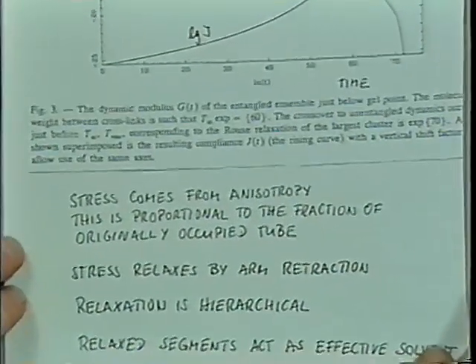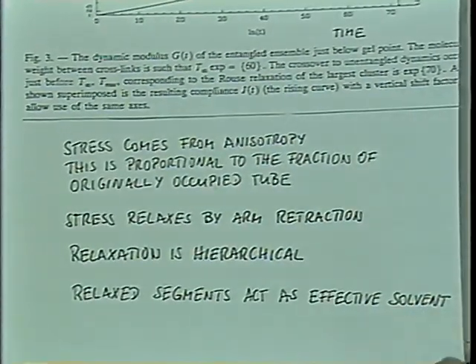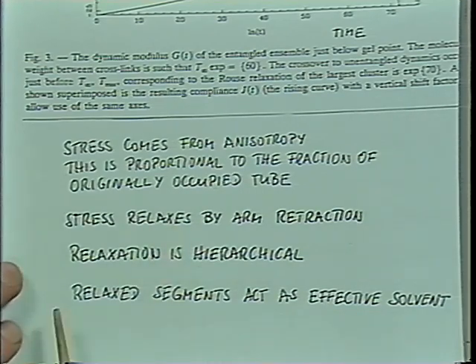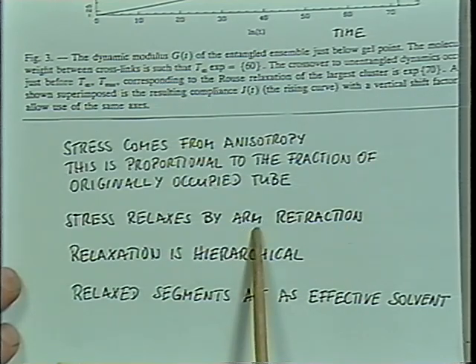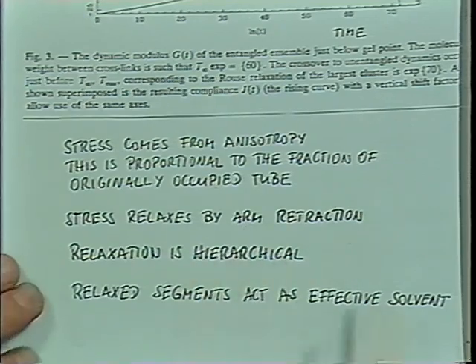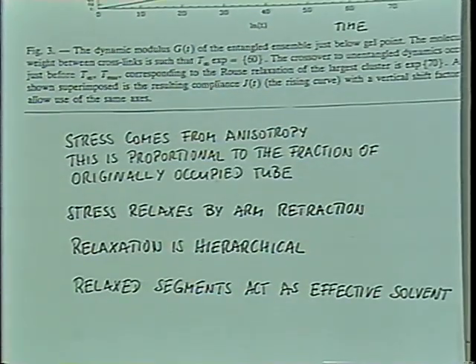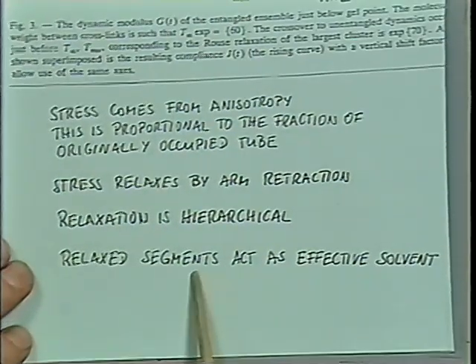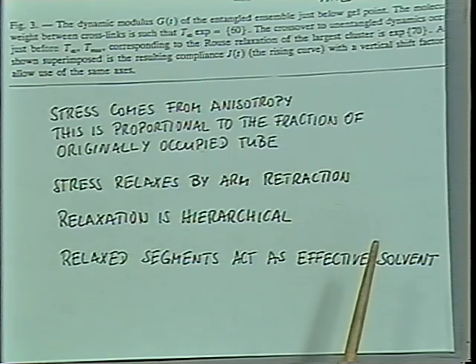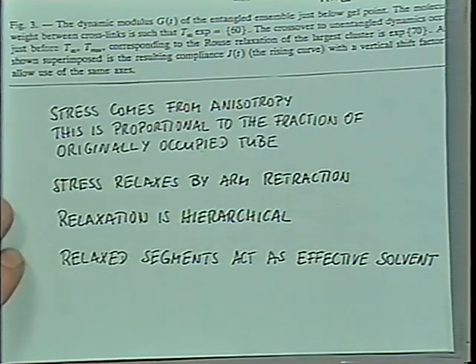So in their model, they're saying that the stress is due to the anisotropy of the chain segments, whether they are at the end or in the middle. And the stress only can relax by motion of the arms. So the arms have to relax, and everything occurs in a hierarchical fashion. And they say that the ends of the chains, even when they are relaxed, are acting as a solvent for the chain. You know, when they're moving out of their constraint, they are not only released themselves, but they are releasing their surrounding. I guess that's what they're saying. So from a molecular dynamics model, these authors are able to describe the relaxation of a complicated molecular structure.